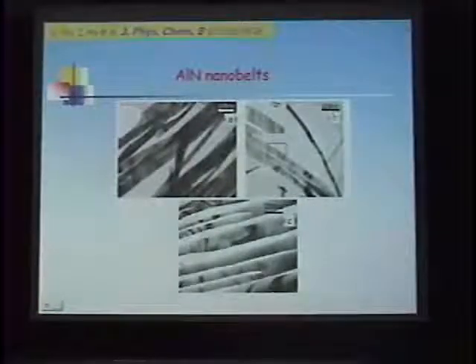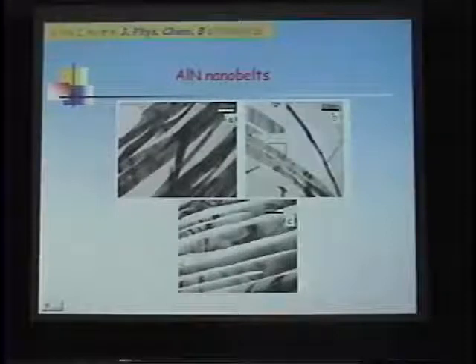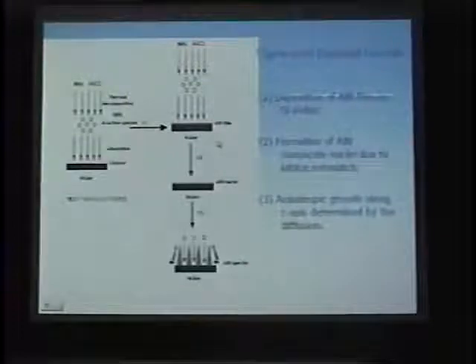By increasing the reaction temperature, aluminum nitride nanobelts could also be obtained. But as we noticed, such morphology is usually in random form. So we would like to align the aluminum nitride. So we use silicon as a substrate and coat a nickel catalyst first, and then we use ammonia and aluminum chloride as precursors to grow the materials.